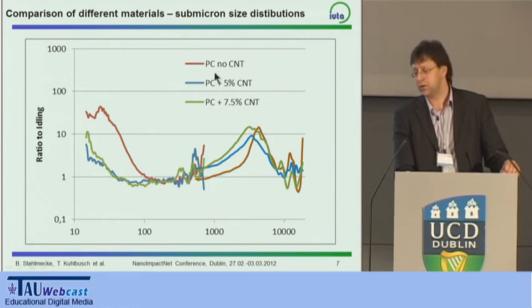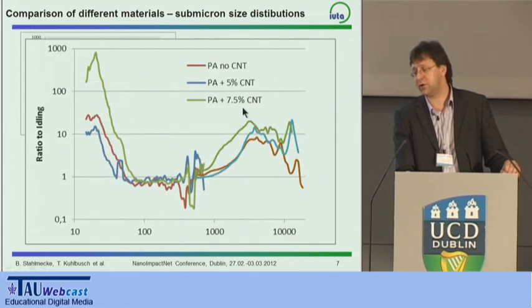Coming to the other one, here with the polyamide, we have the highest mode in the sub-micrometer size range for the polyamide where we have the 7.5% added. And we have a logarithmic scale here, please take account of that. It's pretty similar between the 5% and no CNT for the sub-micrometer range. And we see also a second mode again here for the micrometer size range particles.